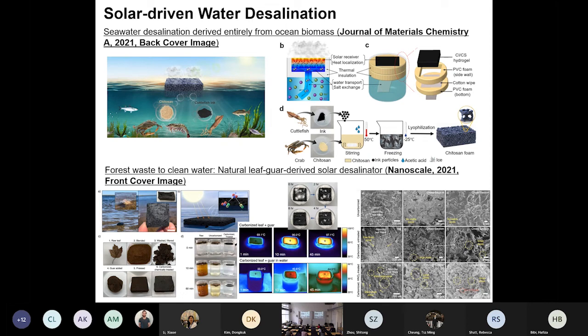To solve this issue, we had to add some adhesive material into the carbonized leaves. But my idea is still to use natural material, so this adhesive material should also come from nature. So we chose guar gum, a type of natural gluing material. We mixed them together. This total material is still made of natural materials, and it works really well.